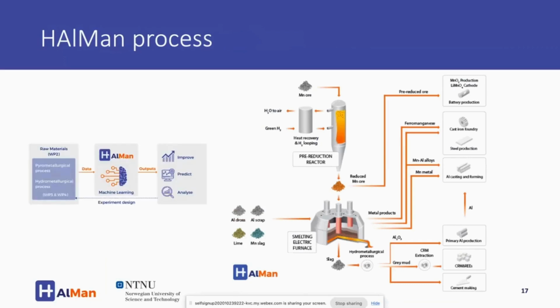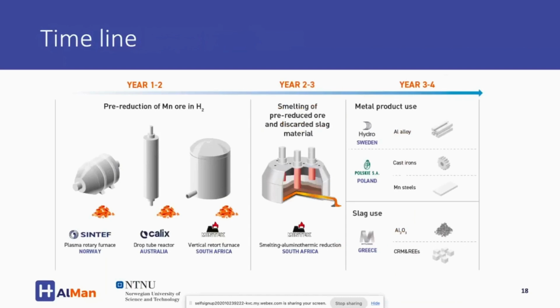Next. And here, as I also mentioned, we do machine learning to make it smart so that we can reduce the amount of experiments and then save time and money. So here you can see what we're doing. 3 different types of reactors are evaluated for the hydrogen reduction part. Here at SINTEF in Norway, we have a plasma rotary furnace, where we use lumpy ore and reduce it down to MnO. At Calix, we have very fine ore. It's a drop tube reactor, so it's micrometer size, and it's falling through this reactor, and hydrogen gas is going upwards, and it takes roughly 2 minutes, and then it's reduced down to MnO.